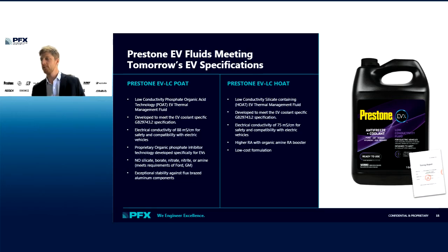So this formulation, as I mentioned before, is unique, built from the ground up out of our R&D facility, a very unique technology. Notably, we were able to produce this fluid without the use of silicate, borate, nitrate, nitrite, or amine, which not many other fluids have been able to do thus far. And then also notable, this fluid has exceptional stability against flux-brazed aluminum components. And I'll show a little bit of that data in a few slides.